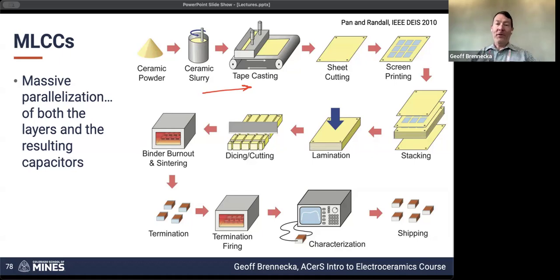I mean, the ceramic powder is what you want, so you're going to have to go through a binder burnout, extended binder burnout in the sintering stage. So keep that in mind as we go through all this, that we've still got 50% of our volume that we have to get rid of that was binder. So that matters from both the process control perspective and the local partial pressure of oxygen perspective. We mentioned that in the last course a little bit. It is also really important from an environmental handling perspective.